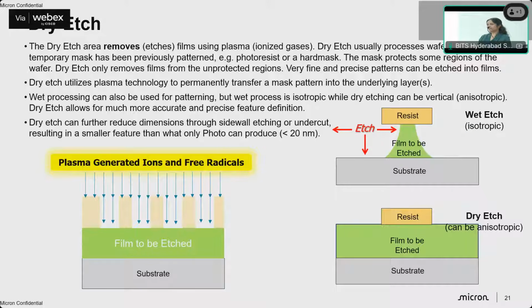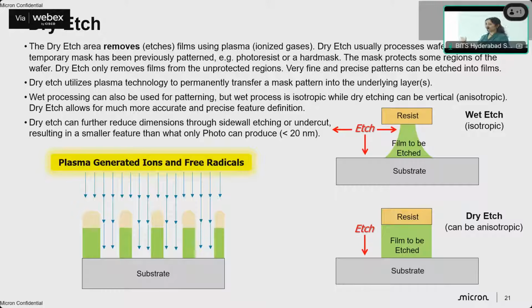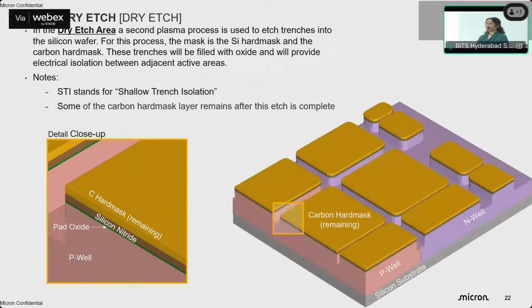There is wet strip, and as you can imagine, it's isotropic. It goes everywhere, which means you have to use it for things that are not specific to a particular layer, but where you're trying to strip the whole layer. Dry etch, however, can be anisotropic. That is, it can be very directional and etch the certain regions that you design. And the photoresist, like I mentioned, has to stand; it will get degraded, but shouldn't get fully removed when we're etching to the bottom.